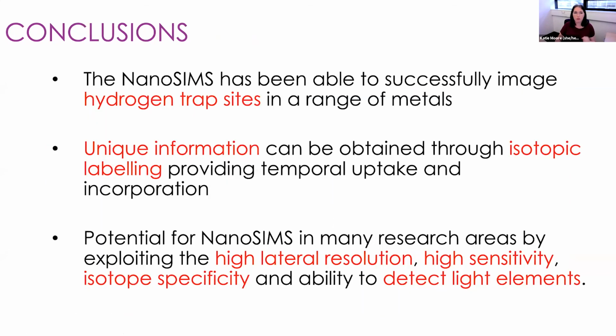So I'll just finish with some very high level conclusions at this point. We've been able to successfully image hydrogen trap sites in a range of different metals: steel, nickel, and zirconium alloys. And we've been able to do so at the scale of the microstructure as well. We can get some very unique information by using these isotopic labels. In this case, I've shown you deuterium and oxygen-18, but we can also get very unique information on biological samples as well by using isotopes. So we can get temporal information about uptake and incorporation.